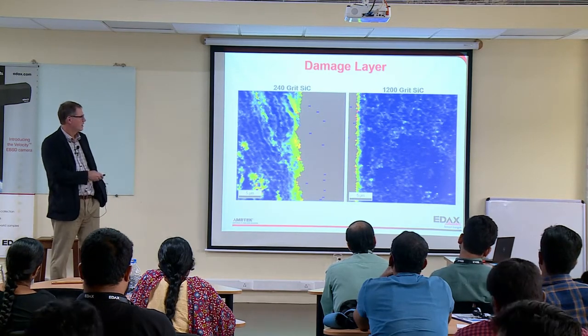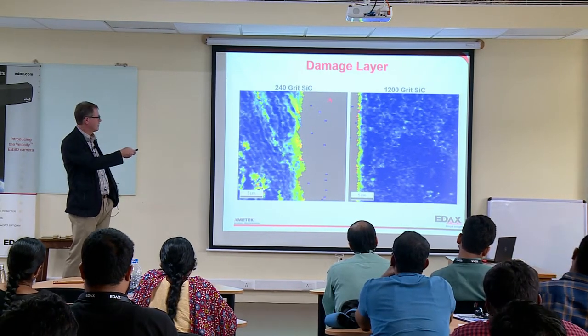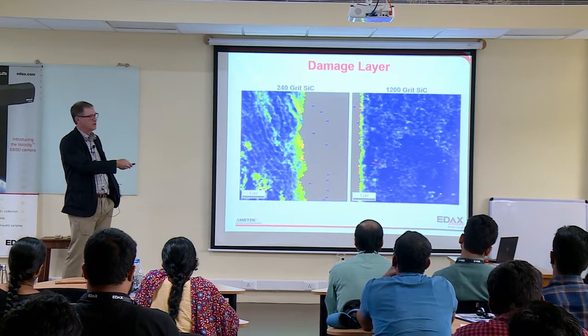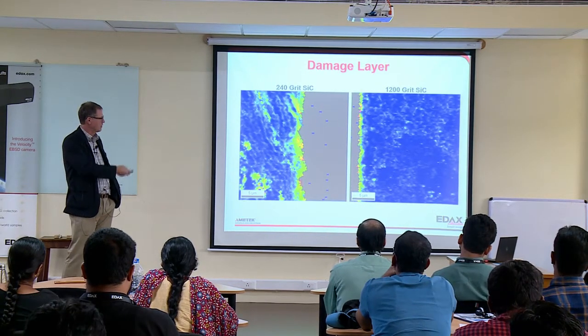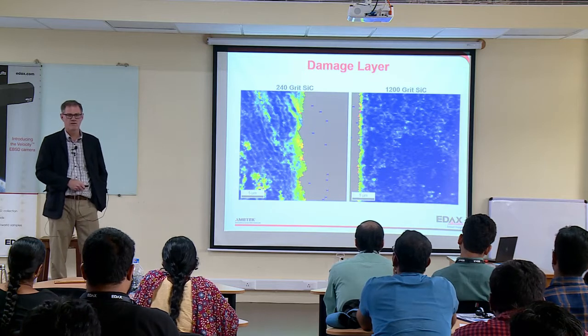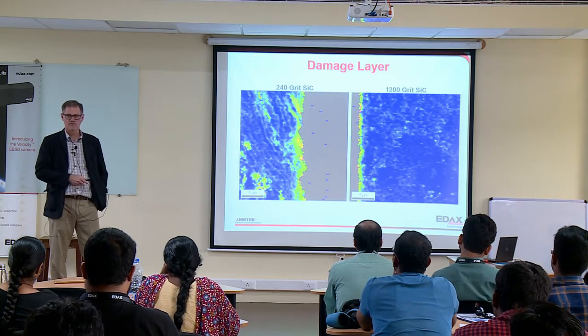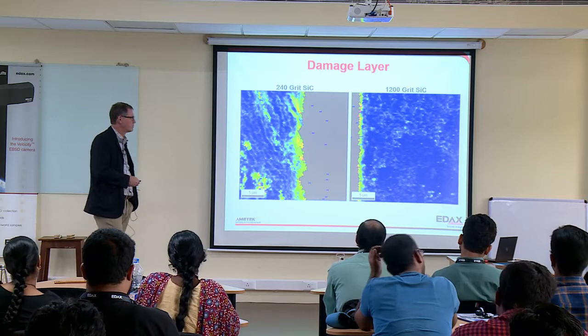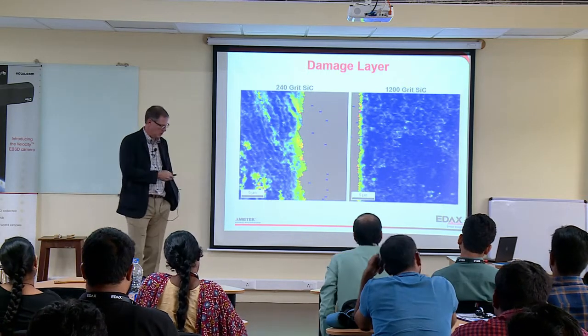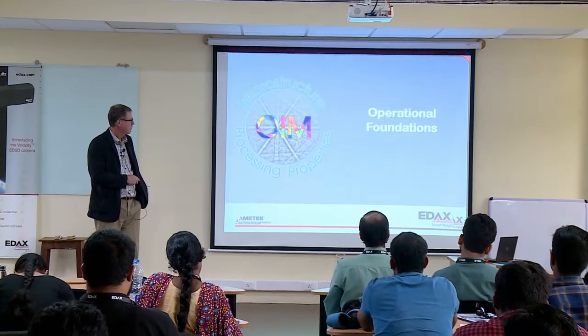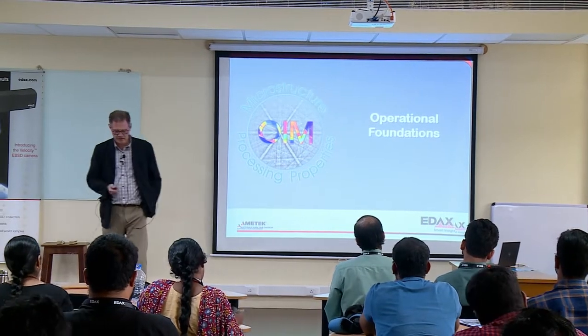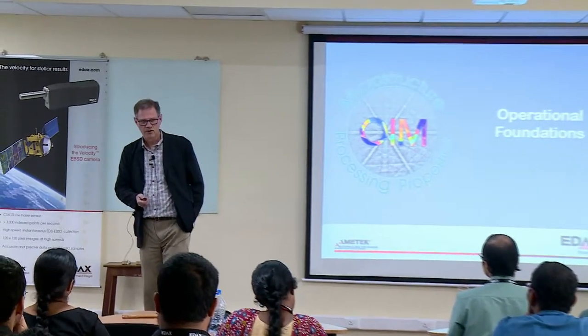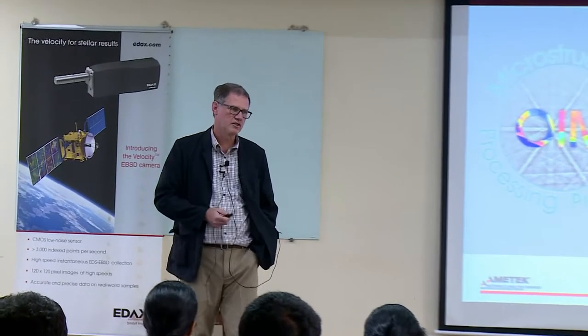And so our electron beam has to get through this and back out. And so if we have a deformed layer on the surface, it's very much going to affect our patterns, because EBSD is very much a surface-sensitive technique. And so it's important to prepare samples in such a way you can get rid of that. So if you need more details on sample preparation, I would check our website. There's some good information there, and a couple of webinars, I believe, on sample preparation in a lot more detail than we have time for during my visit.